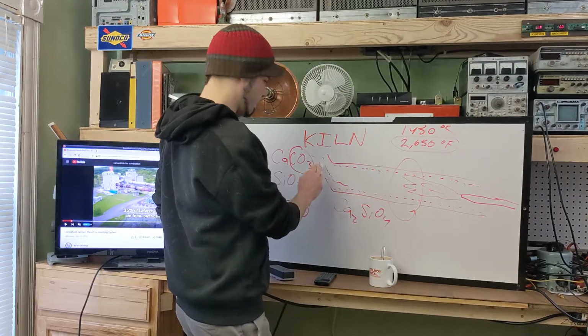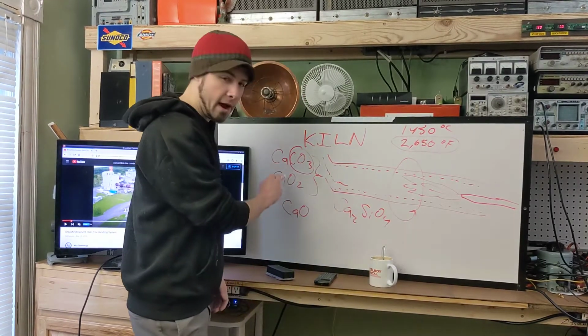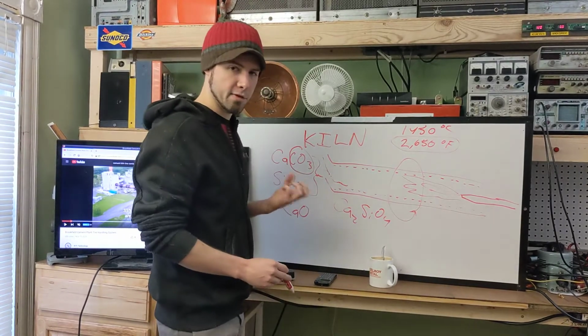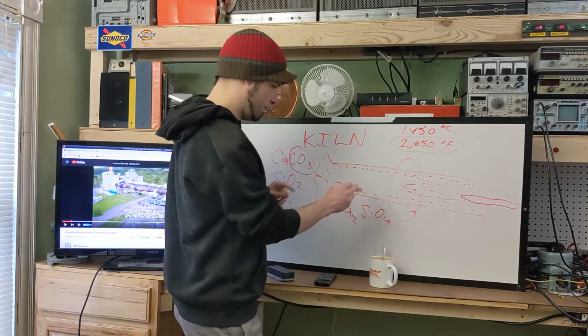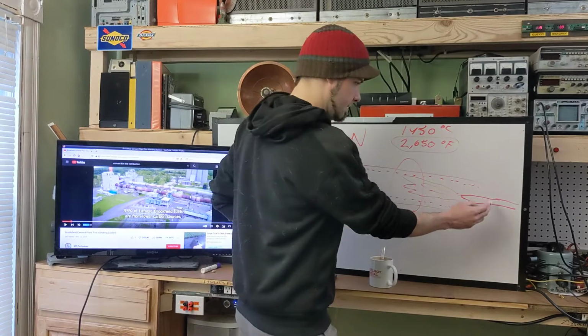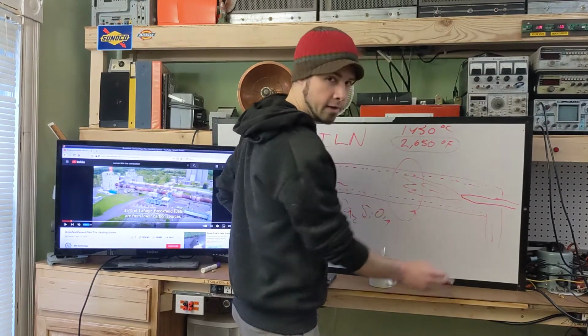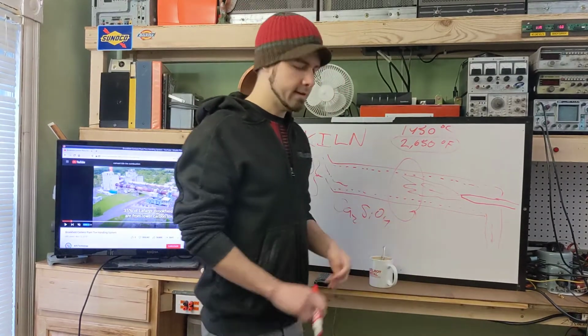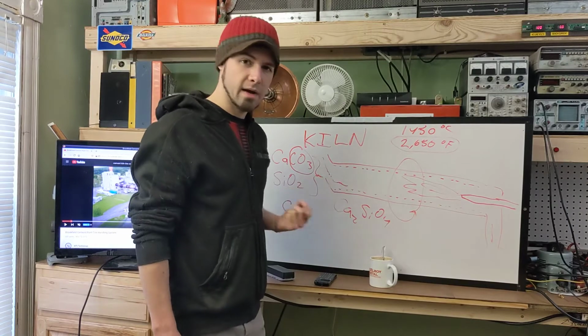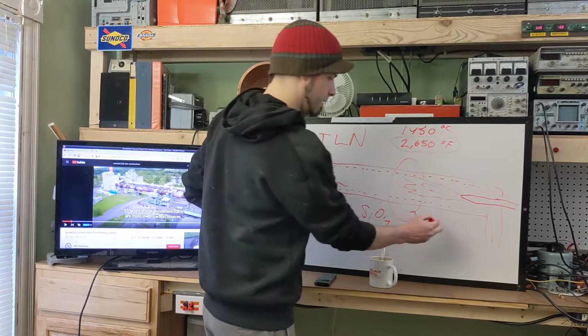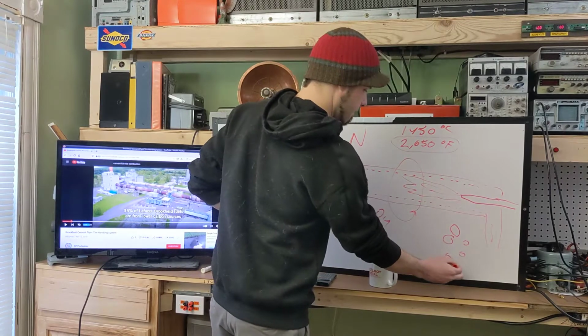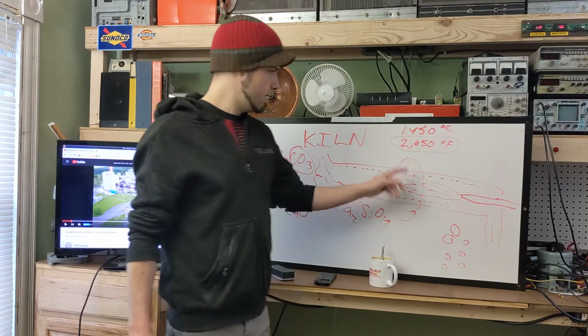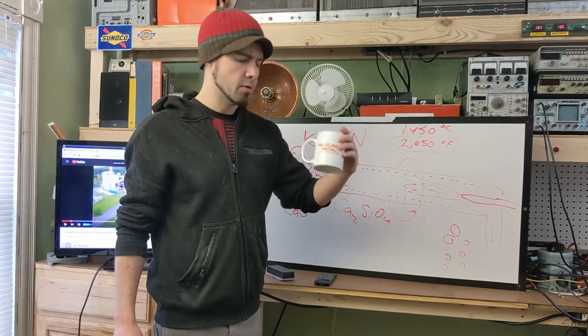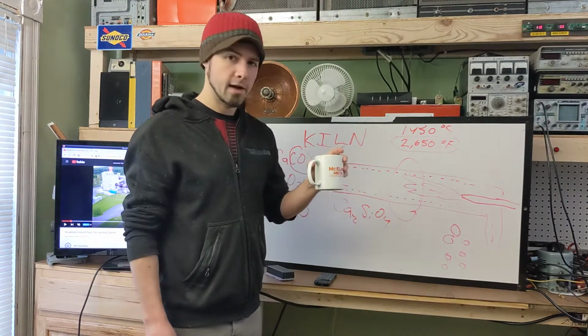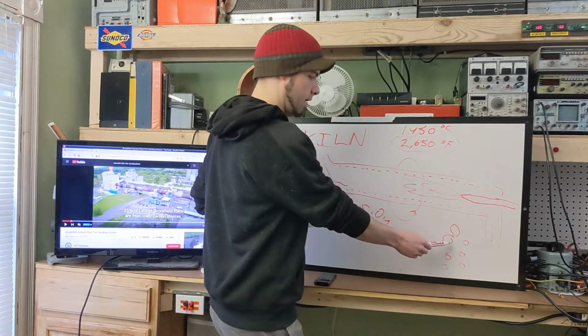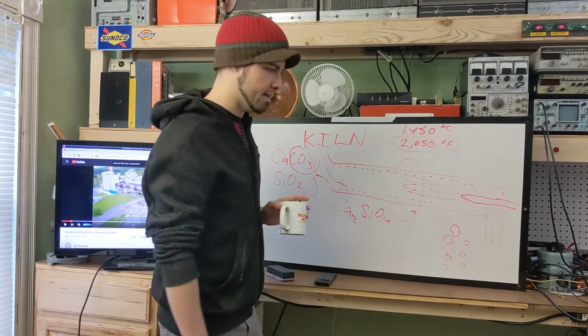So at the end of the kiln, obviously we put in powder. These materials are in powder form. They're very finely ground up to give you the surface area for the chemical reactions. But as it tumbles through here, and it falls out this end right here into what's called a clinker cooler, the cement has formed little balls. So they're probably about 1 inch in diameter or so from what I've seen in the videos. The clinkers, they're little balls of gray stuff. Because as the material has gone through here and hit this temperature, it is actually fired sort of like the clay in this cup. And we have a ceramic, kind of clinkery, kind of agglomerated mass of stuff.